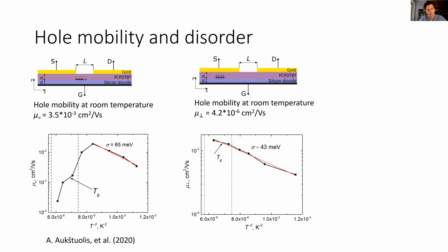So we could do all the measurements live in the heating session. Two things here: the mobility itself is higher in the parallel direction, but around 72 degrees Celsius, it starts to decrease really fast. So this was another interesting point of this material.